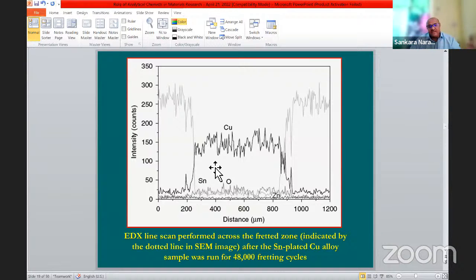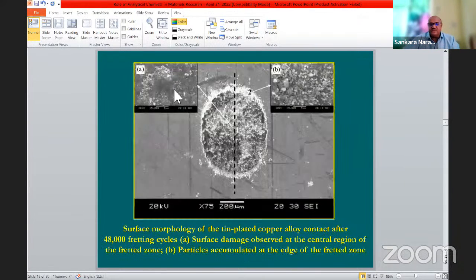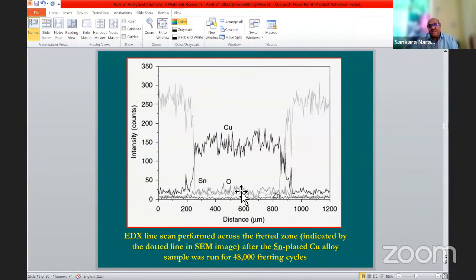And we did EDX line scanning across the fretted zone. Across the dotted line, we did the EDX line scanning. What is the EDX line scanning telling us? You can see this is the line for tin and this is the line for copper. This is the fretted region. In the fretted region, the tin has come down from here to here. In the other regions, tin is very high. In the fretted region, the copper is very high. What does that mean? The tin plating is more or less completely removed, and the underlying copper is exposed. So the coating is already removed, and you can find some oxygen.